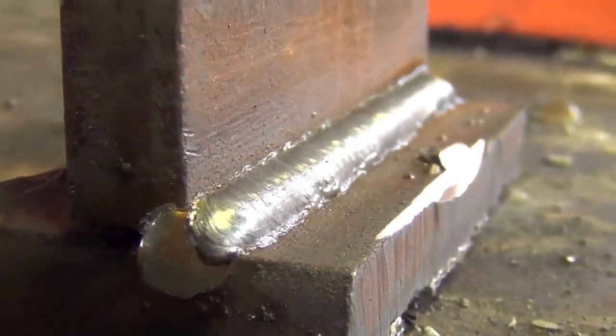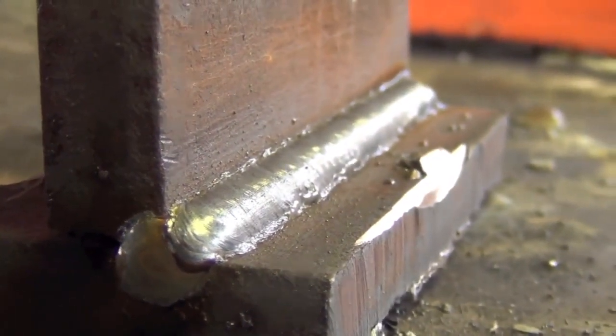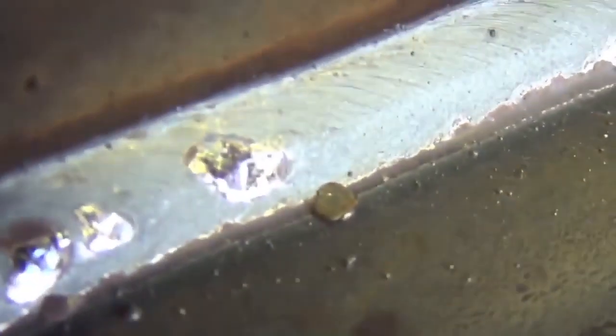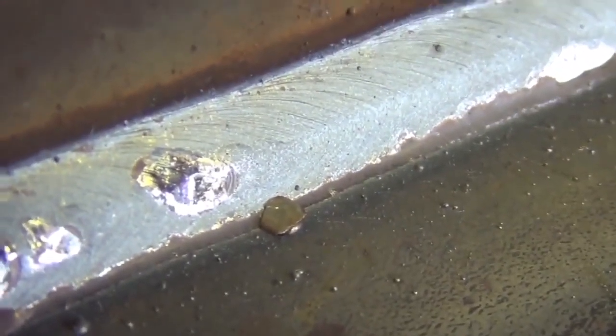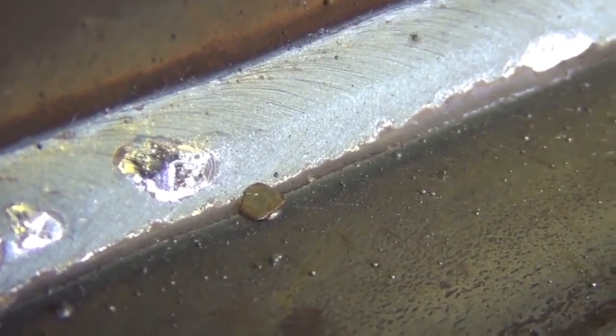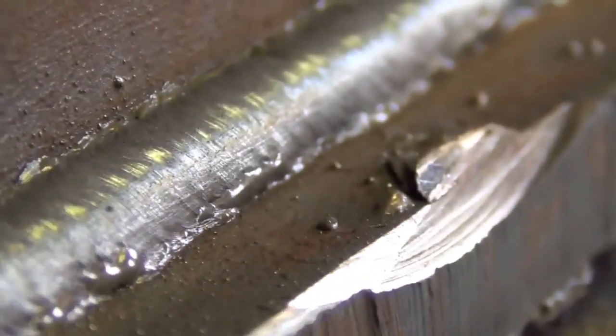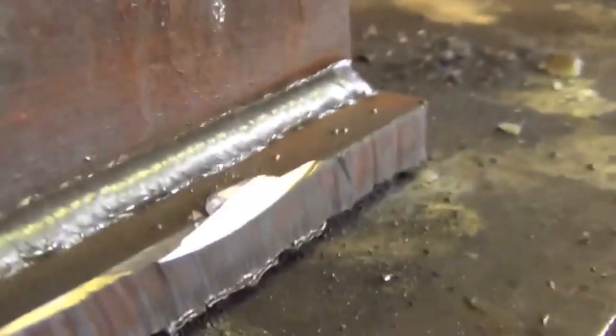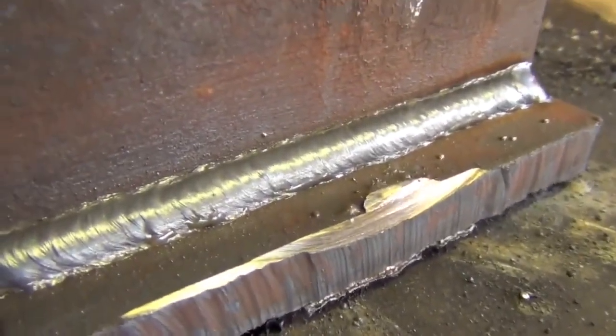We're not tying into our base metal, and the filler metal, the MIG wire, is just piling up on top of itself. As you can see, if you look along the bottom toe line, it's just a nice smooth transition from weld to base metal in our not too cold joint. And here, there is no transition whatsoever. Let me get this from an angle. Yeah, there is just no transition whatsoever. It's a sharp ridge, and you do not want that at all. So if you're running too cold, well, that's what it's going to look like.